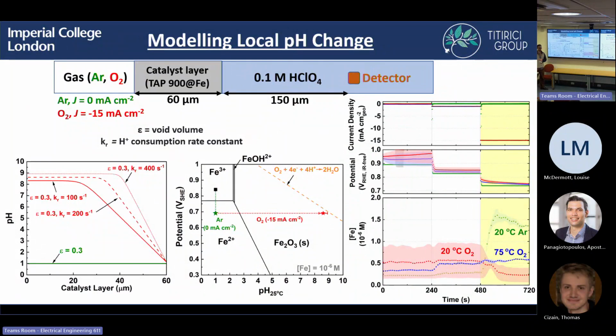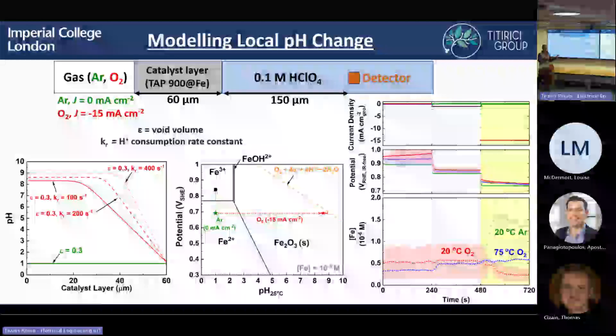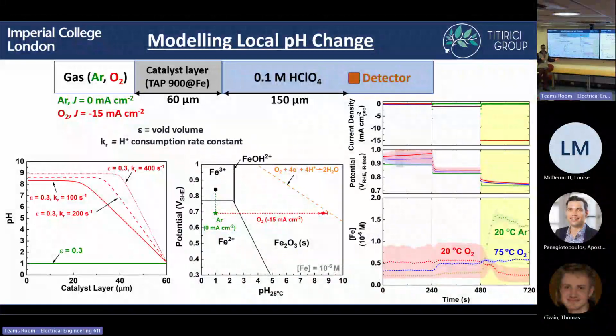Also, the group in France has found that depending on the type of pore that you have, if you just have micropores, you end up with just iron oxides. If you just have mesopores, for some reason you end up with just iron particles. In our case, we have micro and meso, and we end up with iron oxide, but there seems to be some effect of the type of pore that you have here.